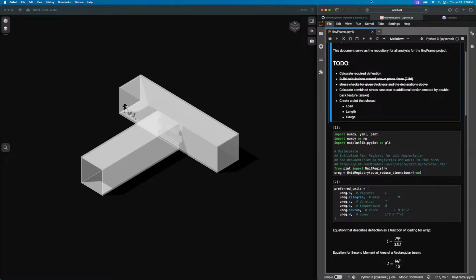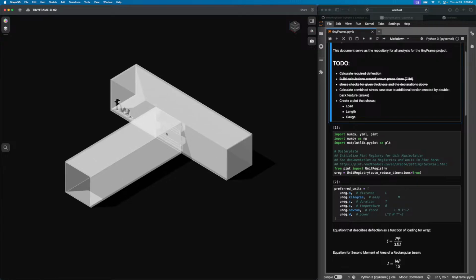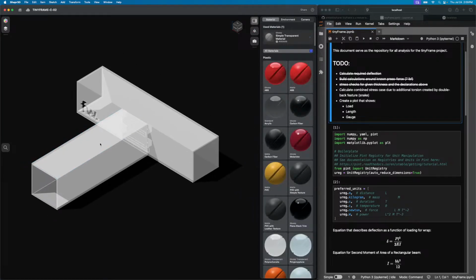So you get what's called a heat affected zone around the weld area. And that's bad because your 38 KSI yield strength on aluminum goes to like 9 or 15 KSI. So you lose more than half your available strength. Believe it or not, what we're looking at here, these two tubes being joined, it could be that this is actually stronger than if you had welded it, interestingly. So we're going to figure out what the weld strength is going to be, and then figure out what the pull and push strength of this joint is going to be.